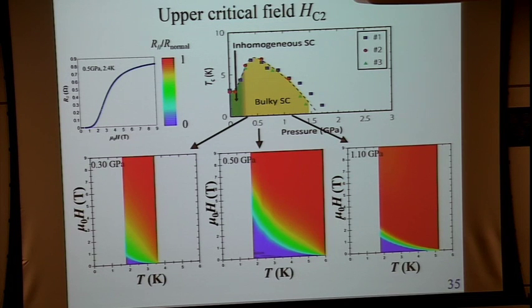If the system is dirty, such a fractional, incomplete superconducting volume would be maintained even at high pressures. But in this case, at high pressures, superconductivity is very clean. So I'm not sure about the origin of the inhomogeneity. But the characterization was made at zero magnetic field. So FFLO appears in the high magnetic field. If you mean FFLO, FFLO-like...